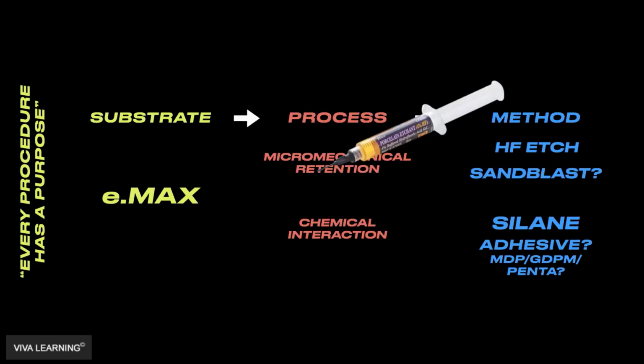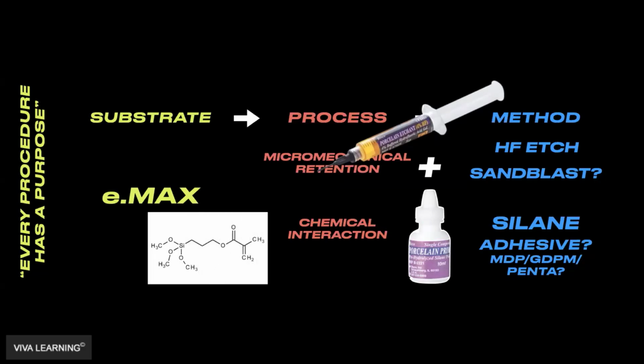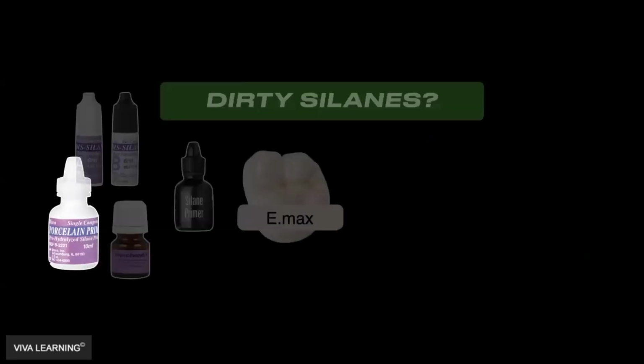Now, silane works best with Emax, right? Because what does silane do? The silane, the silica and the methacrylate is what combine together here. So silane works really well, making this better than MDP or GDPM. The pure silane is your very best that you get with lithium disilicate. Whenever you can have pure silane, those are the highest bond that you get.